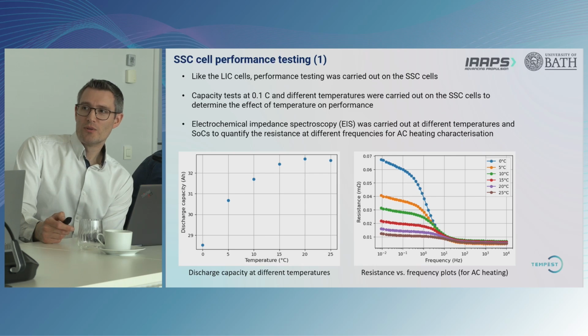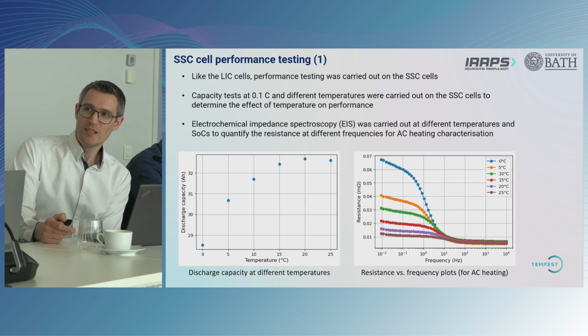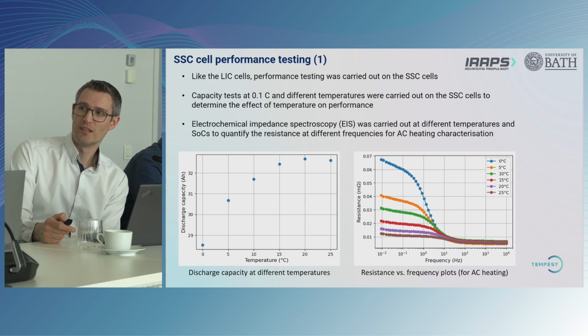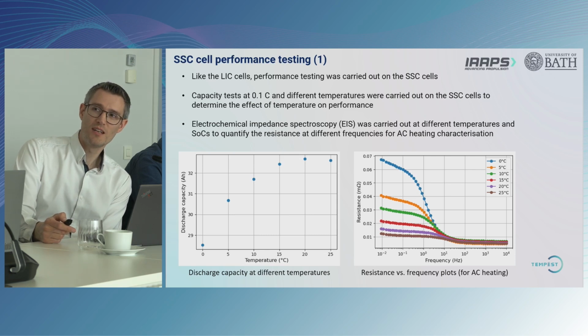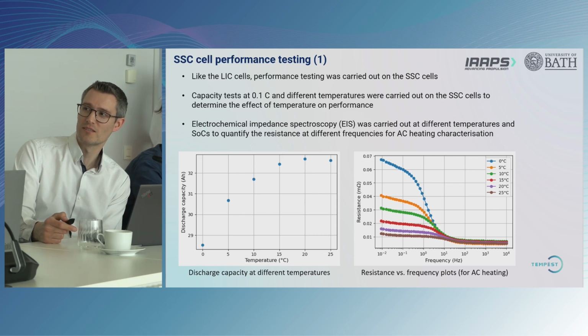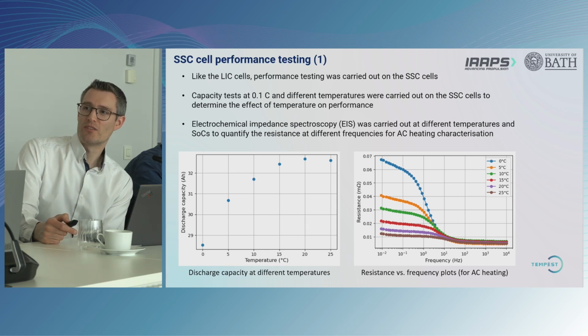So finally, to look at the performance of the solid-state cells, we performed a characterization of the solid-state cells from ABEE, looking at the effect of temperature, and we looked at the discharge capacity and also the internal impedance at a range of different temperatures. And the key thing here was we were interested in the performance at lower temperatures, in particular with a view to understanding by how much we might need to heat the cells to get a good performance out of them. Because one of the common concerns with solid-state technology is the need to operate at higher temperatures.